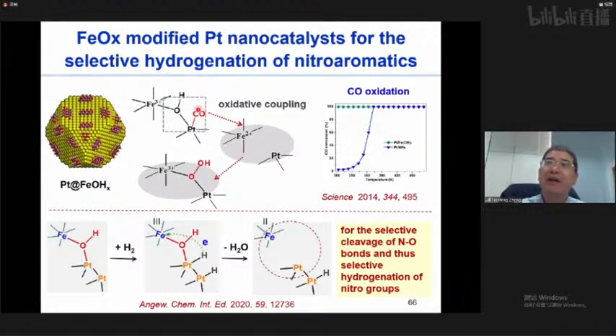So the reaction is rather simple. You see, here is carbon monoxide. We replace it with hydrogen. And then they can do the oxidation reaction. And then basically, the iron 3+ here will reduce into iron 2+. And this iron 2+ is already active enough for the reduction of the nitro group.